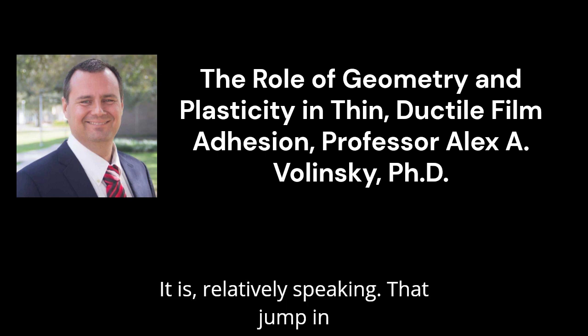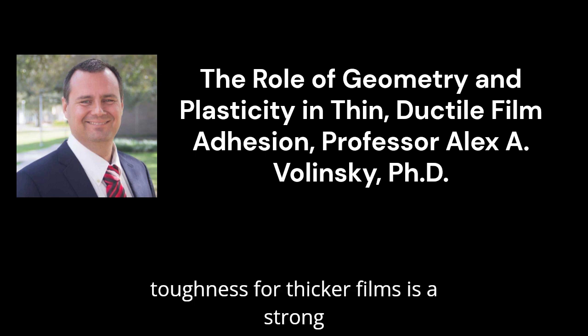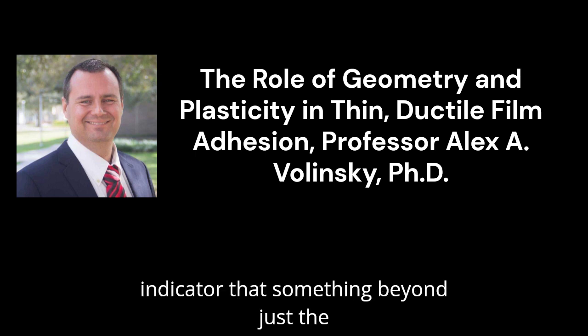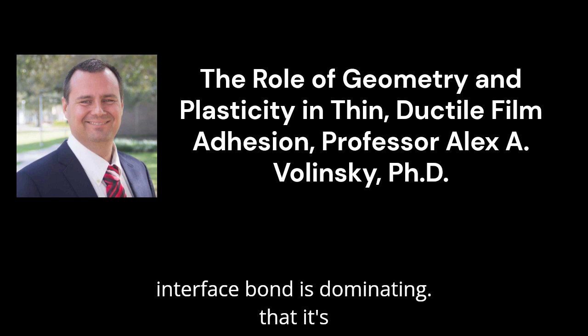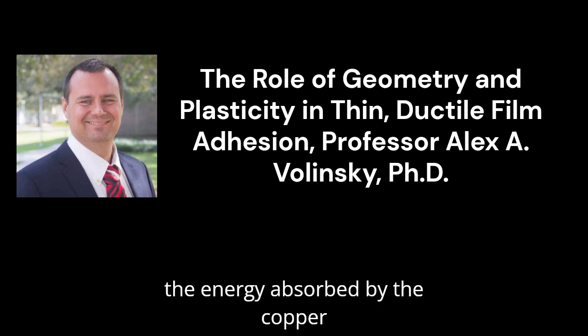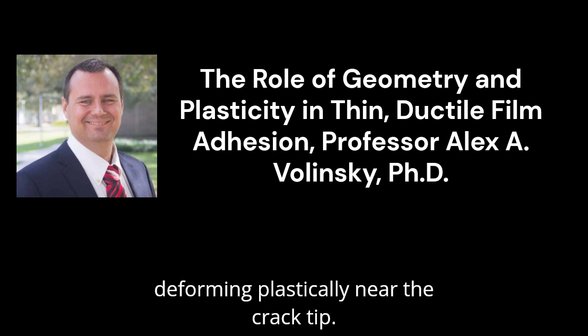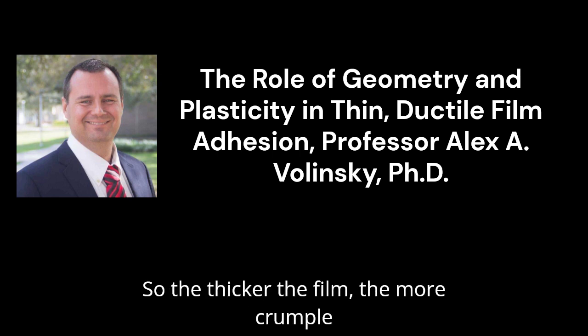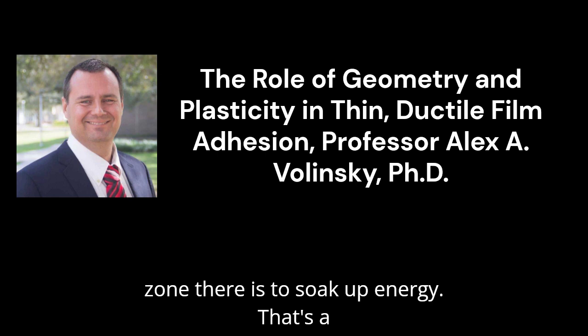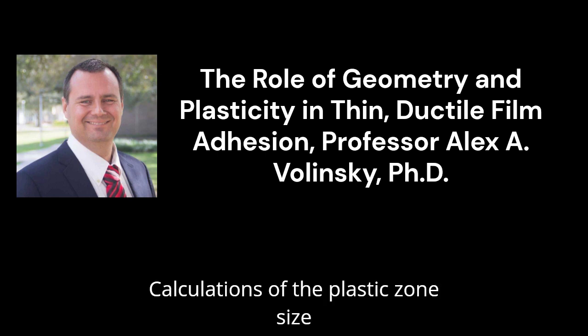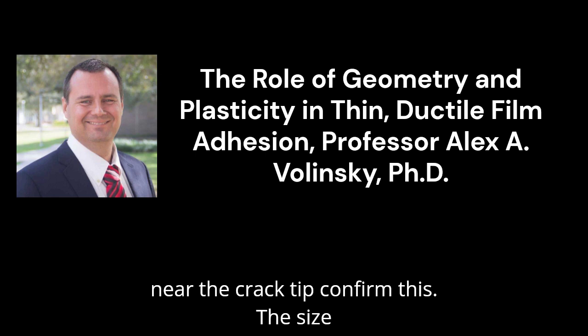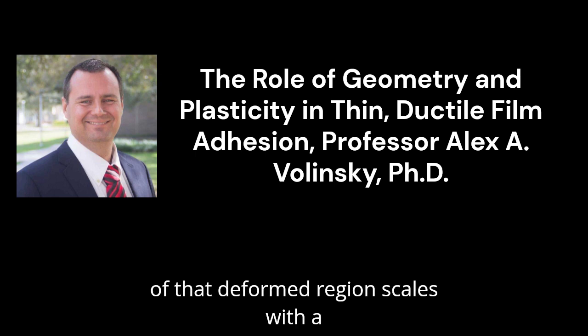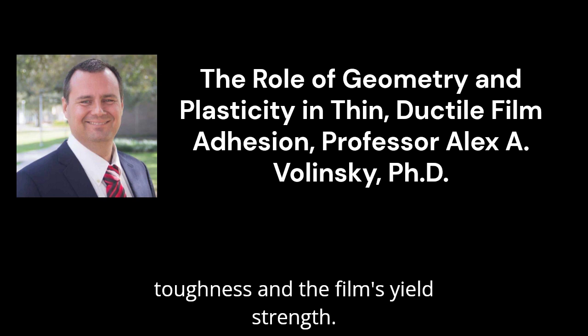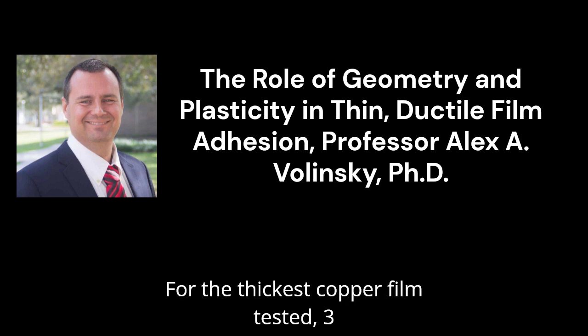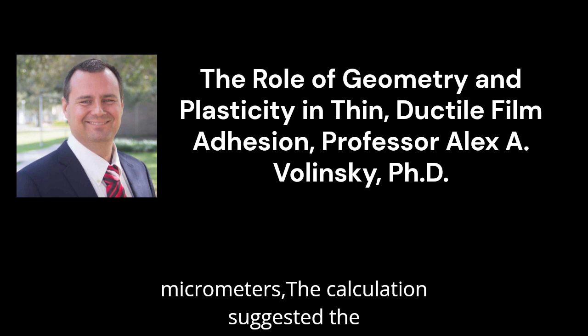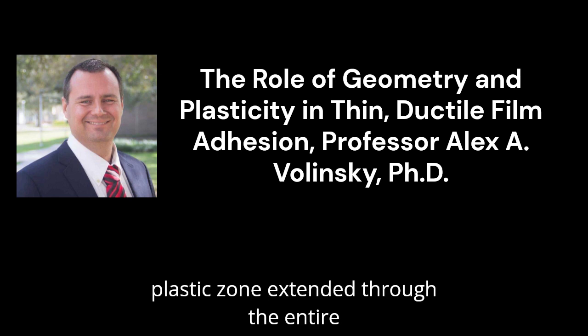It is, relatively speaking. That jump in toughness for thicker films is a strong indicator that something beyond just the interface bond is dominating, that it's the energy absorbed by the copper deforming plastically near the crack tip. So the thicker the film, the more crumple zone there is to soak up energy. That's a good way to think about it, yeah. Calculations of the plastic zone size near the crack tip confirm this. The size of that deformed region scales with the toughness and the film's yield strength. For the thickest copper film tested, 3 micrometers, the calculation suggested the plastic zone extended through the entire film thickness.